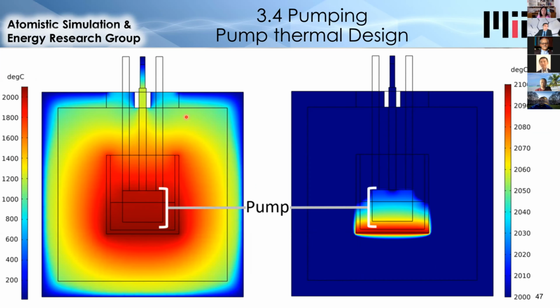Another thermal profile is shown here, which is of the pump and the tank enclosed within about 1 foot of insulation. And you can see that, most importantly on the right, even within the pump, which you would expect to be relatively isothermal because of the high thermal conductivity of graphite and the silicon, it actually experiences about 100 degree temperature gradient from the top to the bottom of the pump. And what this means is that we could experience the same dissolution, non-isothermal circulation issues that we saw in the previous experiment, where graphite is dissolved in the hottest area and then deposited in the colder area.